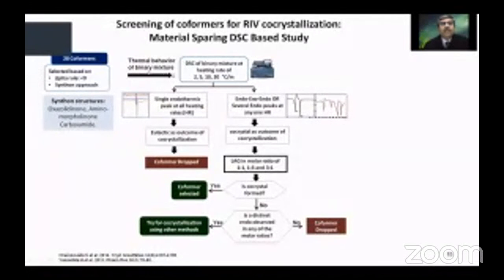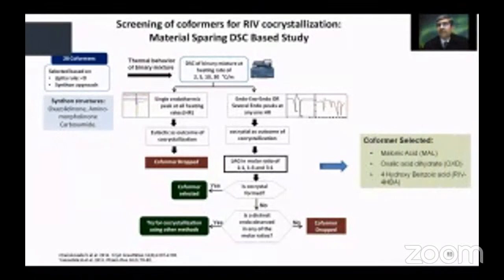Thermal behavior of the binary mixtures of the coformers with the API was assessed using the DSC at different heating rates, and this was the decision tree that was adopted to choose the coformer. And if a co-crystal was formed, that coformer was chosen and taken forward. But if the formation was rejected, we did not take that coformer further. And as I already told you, these were the 3 coformers that were selected: malonic acid, oxalic acid dihydrate, and 4-hydroxybenzoic acid.